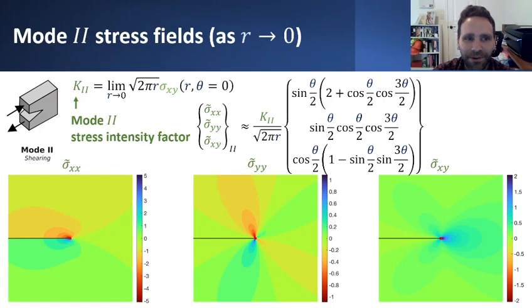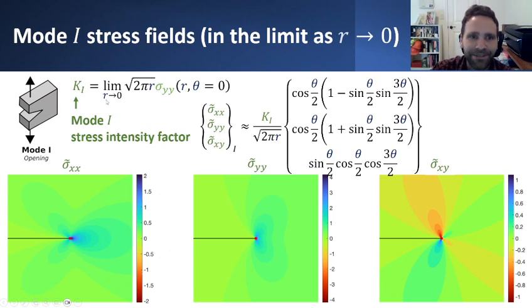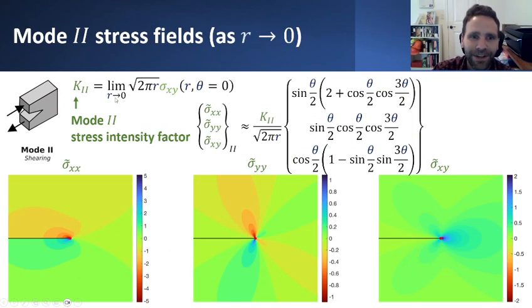And if you looked at mode 2, this shearing mode of deformation, it looks a little bit different. But still, the stress fields all go to infinity. They all depend on this mode 2 stress intensity factor, defined somewhat differently than the mode 1 stress intensity factor, which involved the limit as r goes to zero of the square root of 2 pi r multiplied by sigma yy. Now for mode 2, it's almost the same thing, just switch it out, and it's defined as the limit that involves sigma xy, the in-plane shearing stress.